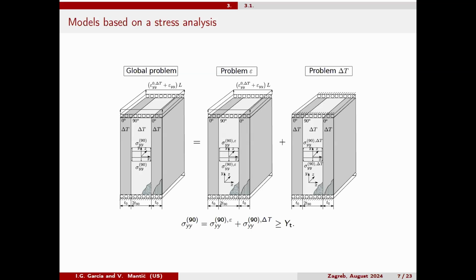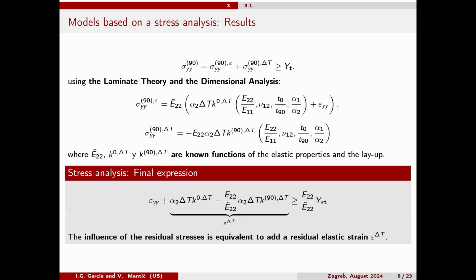So now the laminate is vertical. So we have in the external layers the fibers oriented vertically here, and the internal layer with the fibers oriented through the screen. And we can obtain the stresses, assuming linearity. We can obtain the stresses by two partial problems, one that is more or less mechanical, just applying the mechanical strain monotonically, and another one that is more or less a thermal problem where we just apply the increment, that will be a decrement actually, of temperature. And with the addition, again assuming linearity, we can compare that with the transverse strength of the material. Of the lamina, sorry. So we can use the laminate theory for that and some dimensional analysis.